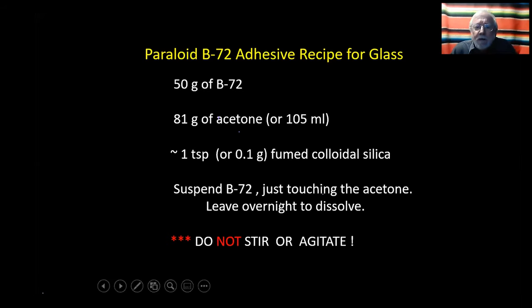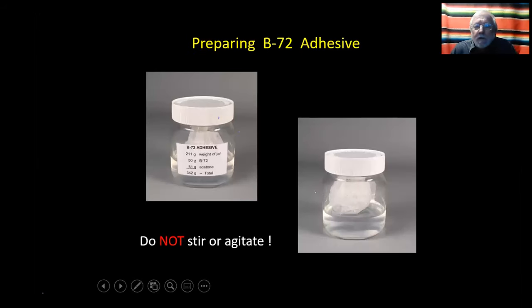Back to making it up, you suspend this in a bag, in the acetone. I add the fumed silica first. So here you're looking at the front with the recipe, and then looking at the back, you have this bag of gauze or cheesecloth with the 50 grams of B-72 suspended in the jar, just touching the acetone.